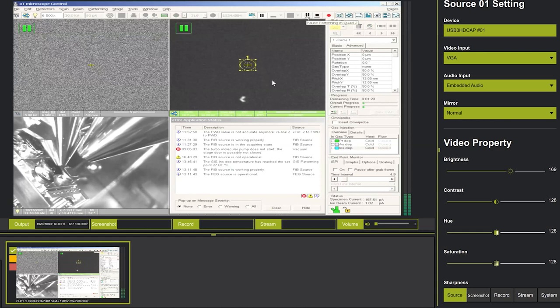The shape I'm making now is outer diameter 2 micrometer, inner diameter 1 micrometer, and the Z depth is about 0.5. This is calibrated for silicon, so it should be close to 5.5 micrometer. The beam condition I'm using is ion beam 30 kV, 93 picoamps. My aperture is getting larger, so it's maybe actually a larger beam now. Please wait for an additional 34 seconds.